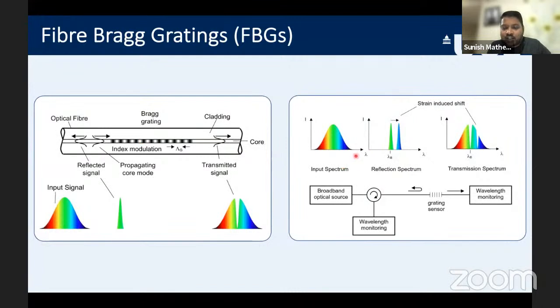So here is just an example of how you build up a fiber optic sensing system using a fiber Bragg grating. Basically, you will have a broadband light source, and then you are looking at the reflection spectrum. When the strain is induced, the spectrum undergoes a change, and if you can calculate this change and also monitor the strain externally, you can then calibrate your sensor so that it is able to measure these changes. So it's a simple system which you can use to build up a sensor for strain or temperature. And these sensors are very popular, and they have been used in many application areas. We also have commercialized systems available with these sensors.